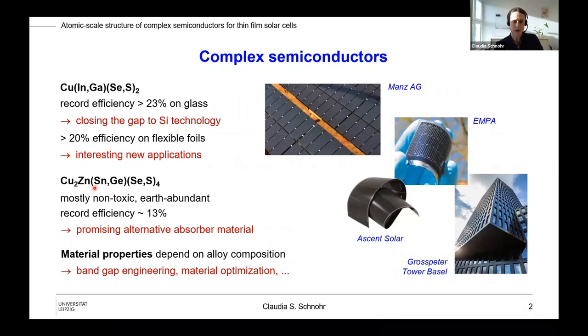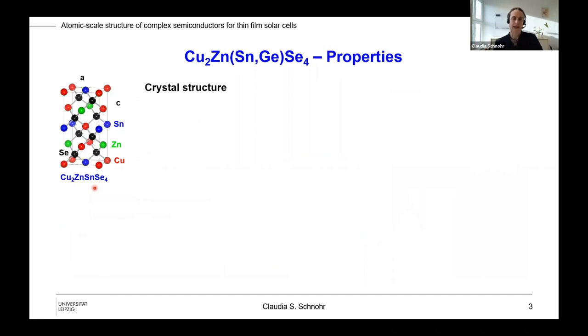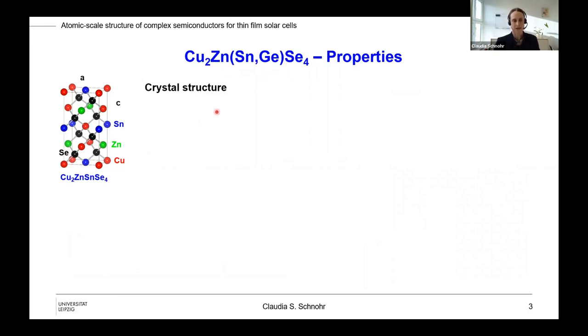By choosing the composition, you can do bandgap engineering and material optimization. I would like to show you this in more detail for the case of the copper zinc tin germanium alloy in selenide. If we look at the crystal structure and start with just a tin compound — copper zinc tin selenide — it crystallizes in the kesterite structure. We have three types of cations: copper, zinc, and tin, all with four selenium neighbors. The selenium has two copper neighbors, one zinc, and one tin.